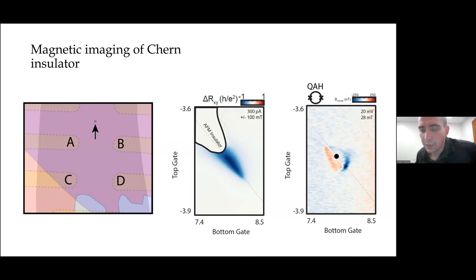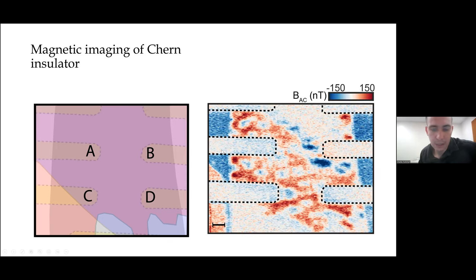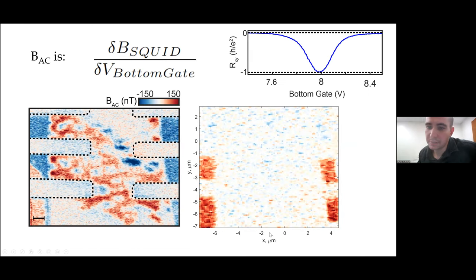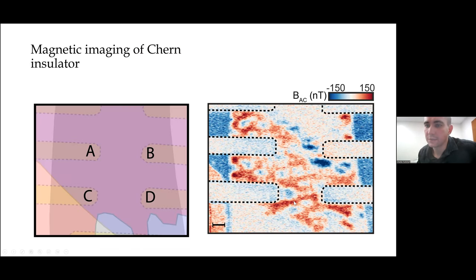So the next thing we can do is use our local probe to probe the magnetic order over the entire device. I'm going to park the top and bottom gate voltage right here and then scan over the regime that shows quantum anomalous Hall between the contacts. And this is what we see in that regime. As you can see, the system is not very uniform. There is only a modestly sized patch of material that shows magnetism. But indeed, it does separate these four contacts that we used for the quantum anomalous Hall measurement.